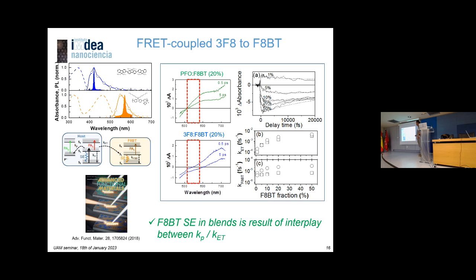So in a way, this verifies the picture, where this is the host polymer, and what you have is the interplay, the balance between these two different rates. When we have efficient energy transfer, we observe emission from F8BT; if the transfer isn't fast enough, we see the formation of a polaron.